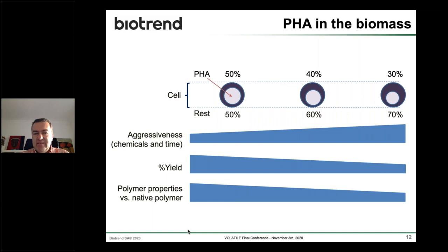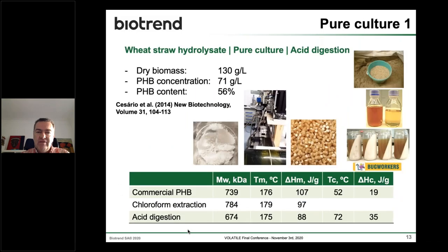And this is depicted here. So the lower the amount of PHA within the cells, the more aggressive you need to be, and the lower the yield will be in the end. And if the yield is lower, it means that we're probably attacking the polymer itself with the chemicals that we use to perform the digestion. And if we attack the polymer, the properties will be changed, because the polymeric chain might be breaking up, or some of the chains of the polymer may be reacting in such a way that the properties are changed.